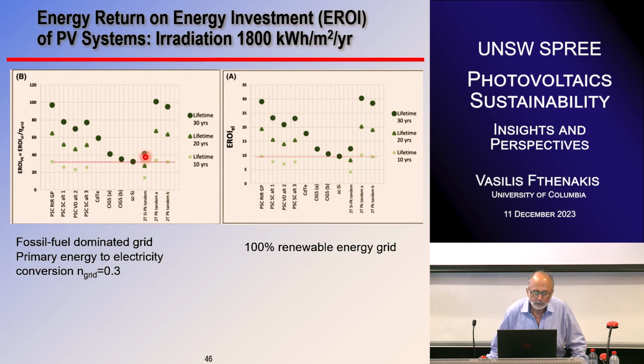So here, I draw a line that is at the level of silicon, 30 year, and you can see that single junction perovskites between 10 and 20 years could give you perhaps the same energy return on energy investment. The actual number is about 12 years. So if they last at least 12 years, they can give you the same energy return on energy investment, based on this data, as crystalline silicon that lasts 30 years. With multicrystalline silicon at the bottom, it is closer to 20 years here. You have to have closer to 20 years of life in order to have the same energy return on energy investment as crystalline silicon.